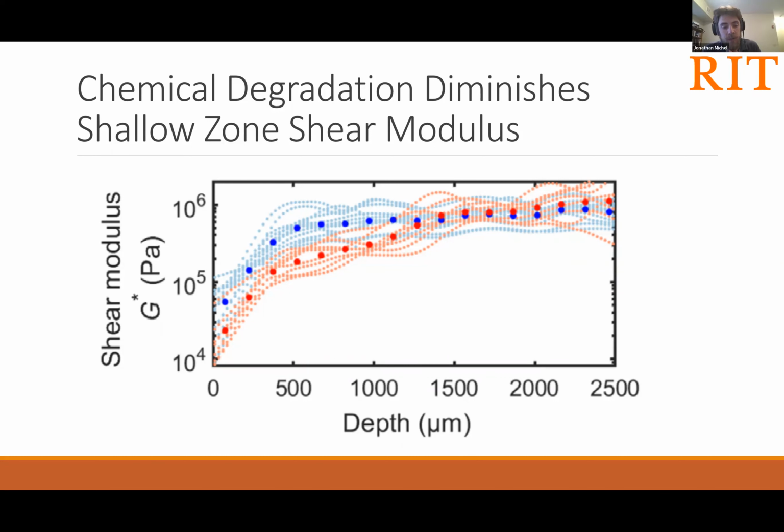Okay, so the gel itself actually has a pretty large shear modulus, on the order of a couple of 100 kilopascals. As I mentioned, this gel is a polyelectrolyte, and previous modeling, for instance using a Poisson-Boltzmann approach, has shown that the mobile charges within this material contribute immensely to the overall shear response of the tissue.